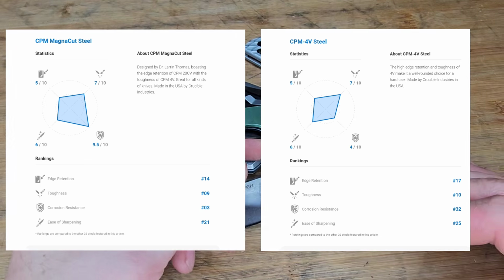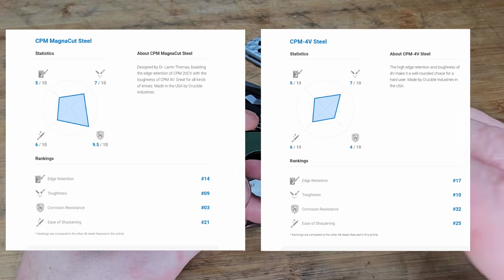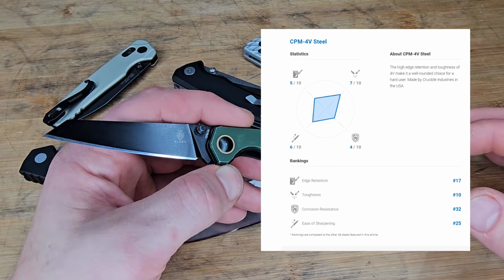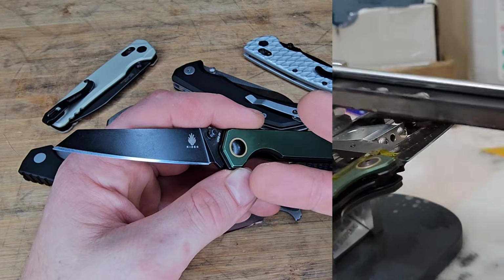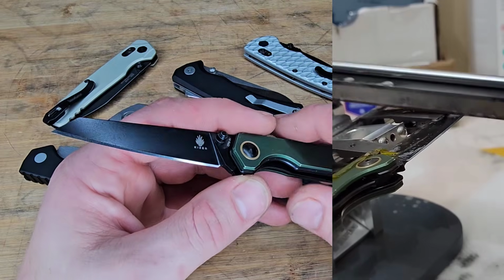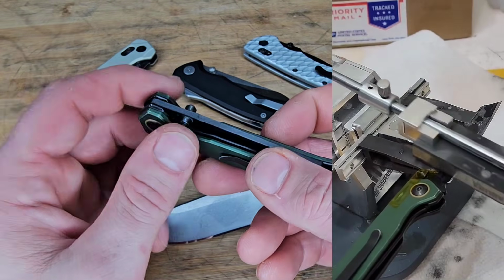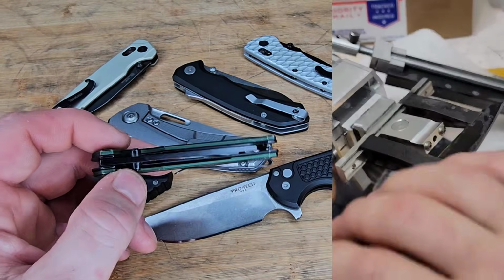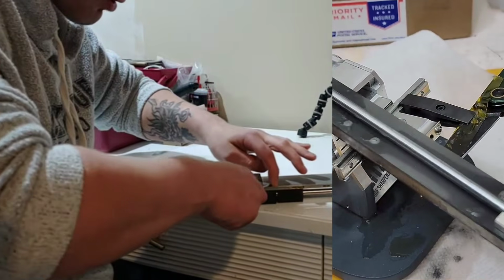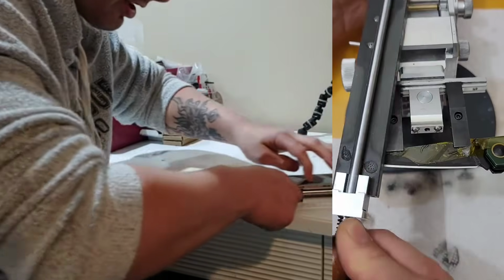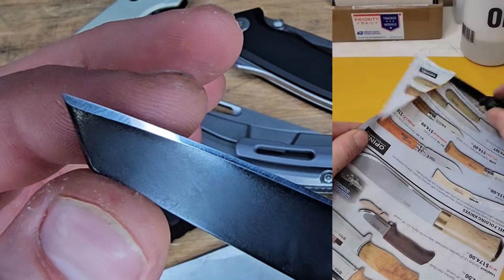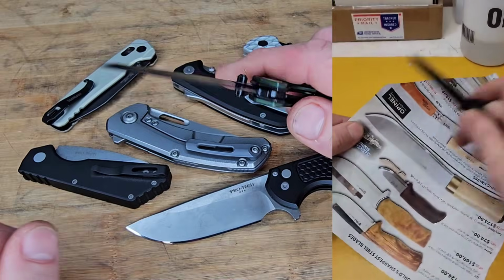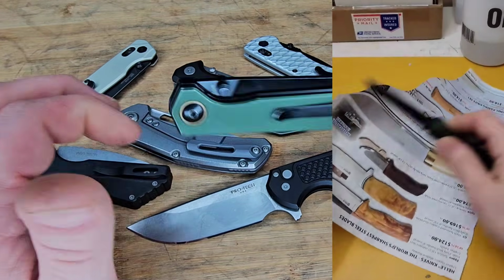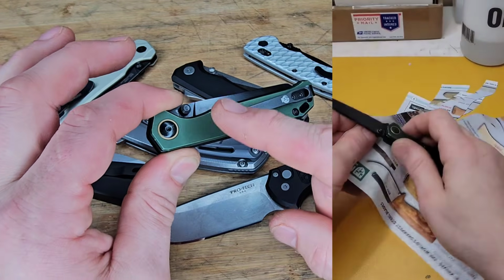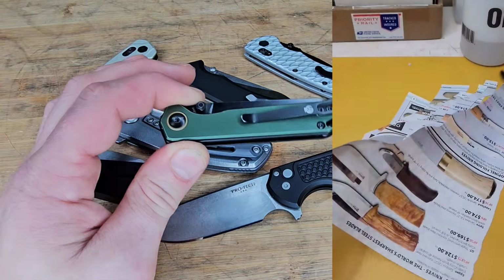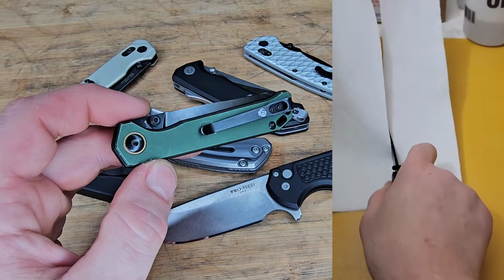Now, 4V has very similar everything except for corrosion resistance. So it basically has the same toughness, the same edge retention, but it is only a 4 out of 10 for corrosion resistance. 4V is an incredible steel, by the way. I freaking love 4V. It takes some of the sharpest edges on the planet, and it loves a polished edge. It will take a low angle polish. Look at this. Just this one alone, man. This thing is so ridiculously sharp. If you want to feel hyper sharp, 4V is a great steel to work with. Like I said, takes low angle edges very well, and you can go all the way up to 5-10,000 grit with no problem. It'll also take a good medium grit edge.